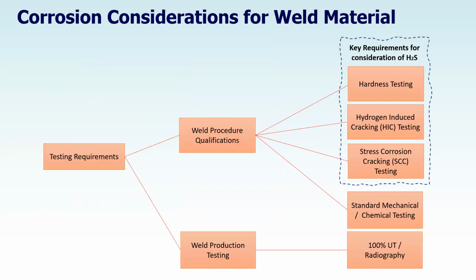Once we've selected an appropriate welding consumable, we'll need to test and qualify that it's compatible with the pipe material. To do so, we do the standard weld procedure qualification trials, including standard mechanical and chemical testing. Further to this, we may be required to do additional hardness, hydrogen-induced cracking, and stress corrosion cracking testing. The production welds will be tested with at least 100% UT or radiography.